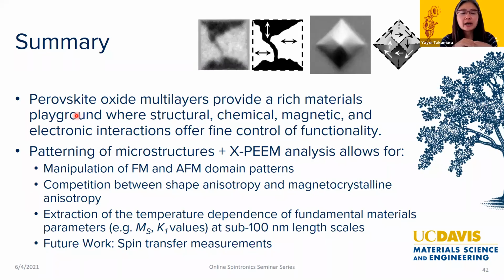Patterning of these materials and using our XPEEM analysis allows us to show that we can manipulate not only ferromagnetic domains, but also antiferromagnetic domains. It really occurs through a balance of different magnetic terms, including shape anisotropy and magnetocrystalline anisotropy.